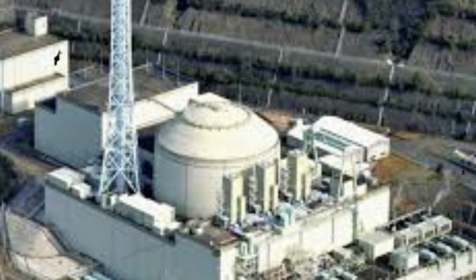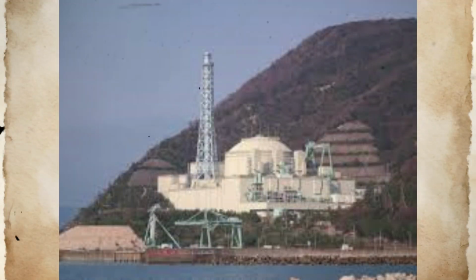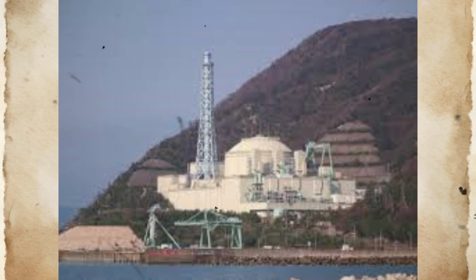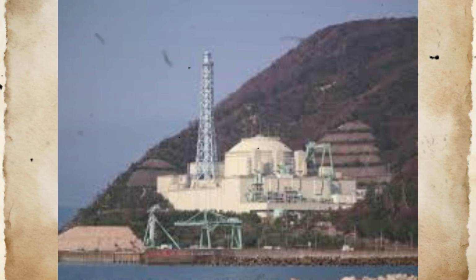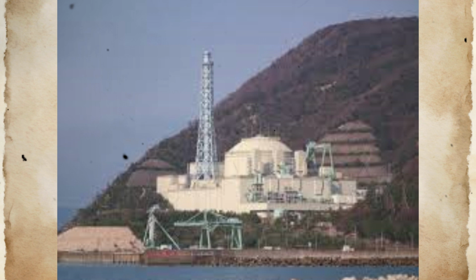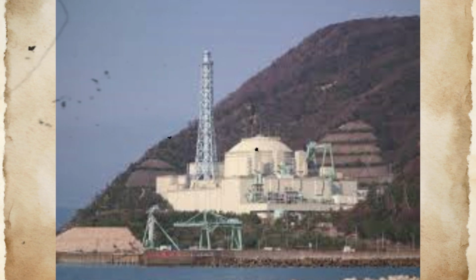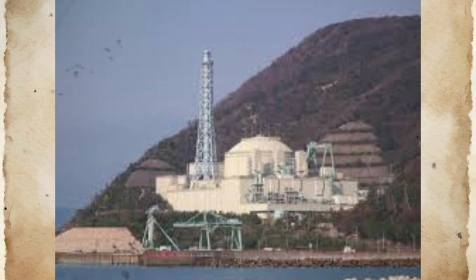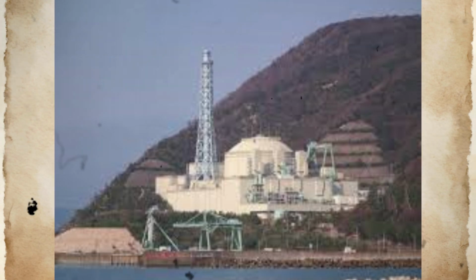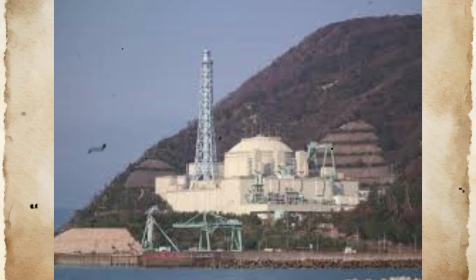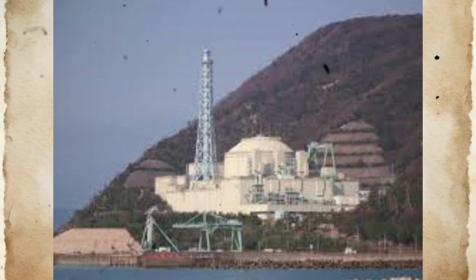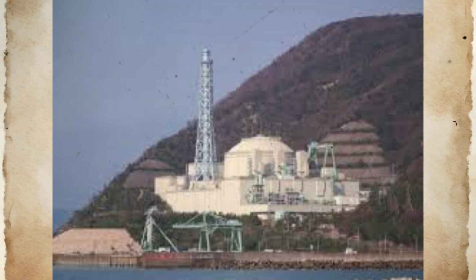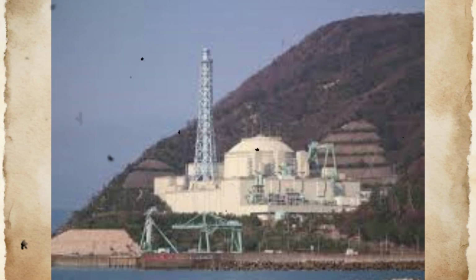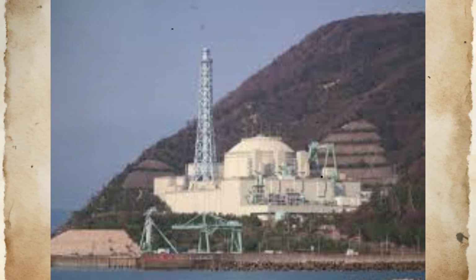Following the manual reactor trip at 2120 on December 8, 1995, Monju operators faced the challenge of maintaining adequate decay heat removal while isolating the failed component in SHTS Loop C. The reactor shutdown had eliminated active power generation, but substantial decay heat continued to be produced by fission product decay within the reactor core. This thermal load required continuous cooling to prevent core overheating, creating operational constraints that influenced every